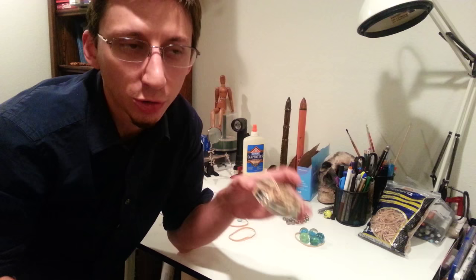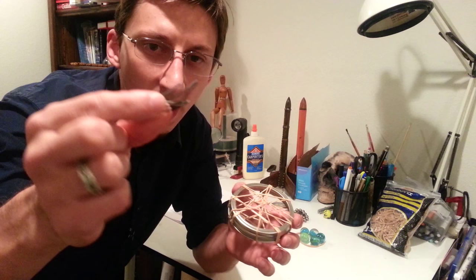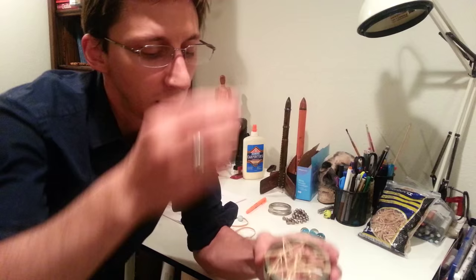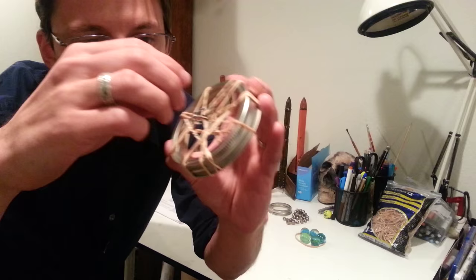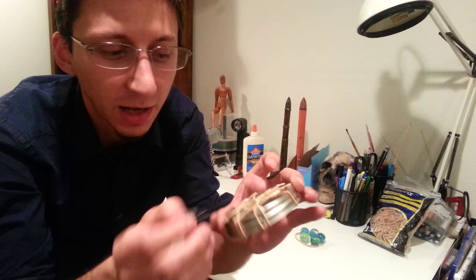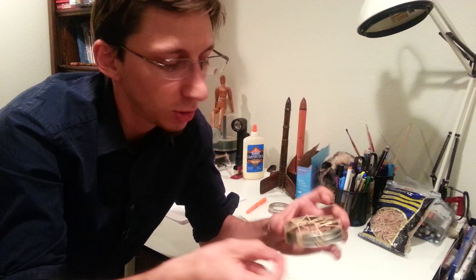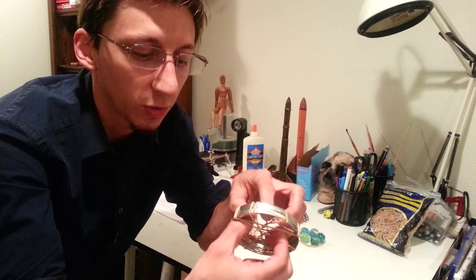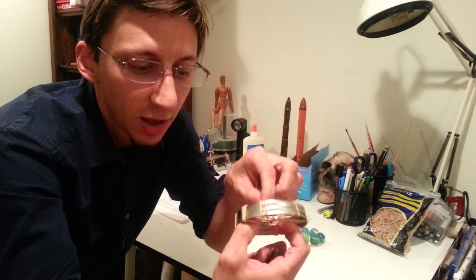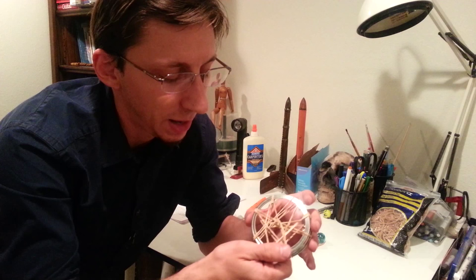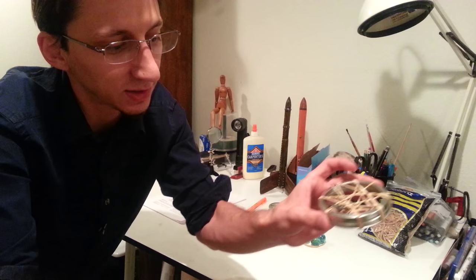It's more of a metaphorical way of approaching the idea, but it's as though the carbon dioxide and the difluoroethane has sort of more hooks on it. So they have a tendency to stick into the latex surface and then get pushed through by their neighbors that are coming in after them. And so this will actually get totally filled up and deform. You might remember from before where the balloon would kind of have this funny texture, and that's when actually the latex would have got completely filled up with the carbon dioxide molecules, and it was actually plasticizing or making rigid the polymer matrix that made up the latex. You'll see with this sort of a thing, even when I drop it, it kind of just sticks. It doesn't exactly fall through as much, because what happens is it just kind of sticks in there and gets stuck.